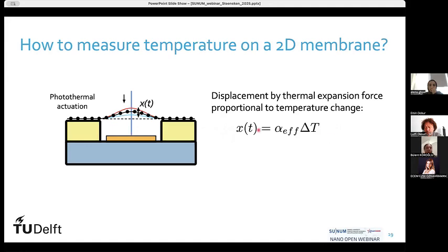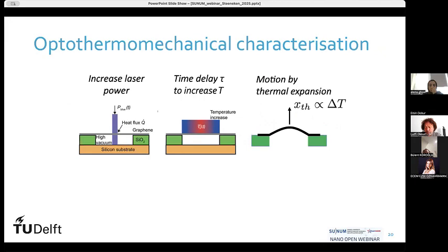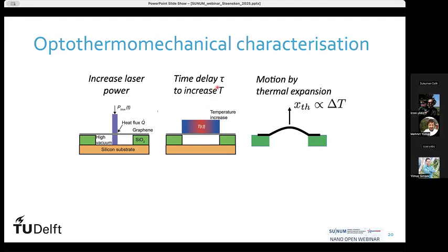This means that we can use this deflection, at least if we're far below the resonance frequency, as a measure of the temperature change. Of course, we need to find this coefficient in between them, but if we're only interested in the time scales at which these temperature changes occur, this relation is enough. So how does it work? We increase the laser power, then it takes some time for the temperature to increase, and the time is characterized by a typical thermal time constant, tau, after which we measure the motion increase, the x.